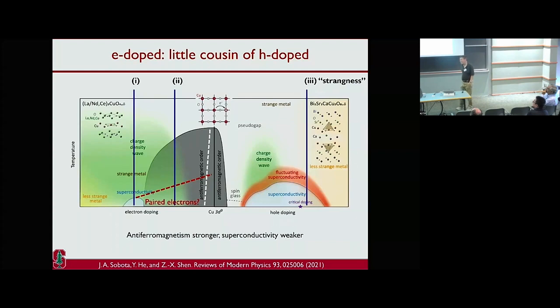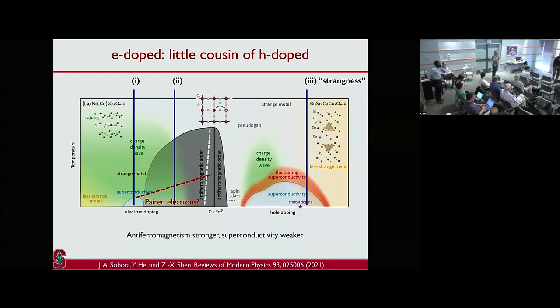Yes. Let me throw in, for 30 seconds, another explanation for your data in the magnetically disordered state, the first part of your talk. Another explanation is that what you see are precursors to antiferromagnetism. Not reconstruction of the Fermi surface, but transformation of spectral weight into where it should be in the magnetically ordered state. A way to distinguish it from reconstruction of the Fermi surface is to do, if possible, MDC at different frequencies, going over the range where you get these new pieces of the Fermi surface which should not be present in the pure normal state. If it's a reconstructed Fermi surface, then the intensity should not depend on the frequency at which you do MDC. If it's a precursor and transformation of spectral weight, then these pieces where you get new extra Fermi surface, their intensity should go to zero as frequency goes to zero. So this is the way to distinguish.